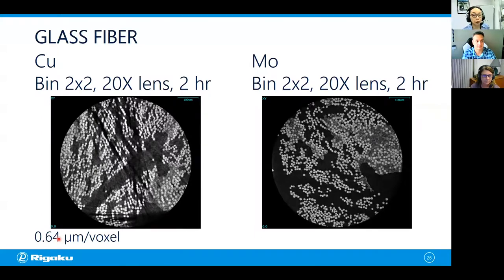You get great contrast. The glass fibers look very, very bright and everything else is very, very dark, which is kind of nice, but you see those streaks coming around or from the glass fibers. And those are beam hardening artifacts.